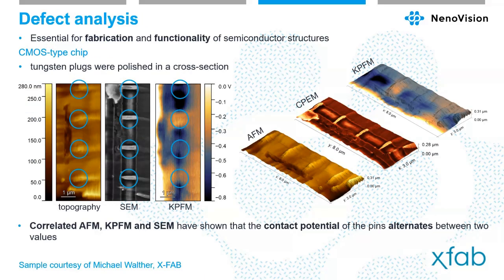So if we have a look at one example of defect analysis, it's, as I said, quite essential for fabrication and functionality of semiconductor structures to analyze the structures for defects. Here is an example of a CMOS type chip, and we can see that the tungsten plugs were polished in cross-section, and then we see that the contact potential alternates. It wouldn't be possible to find it out in SEM or topography because it looks the same, but we need to know it in order to understand how the device works.